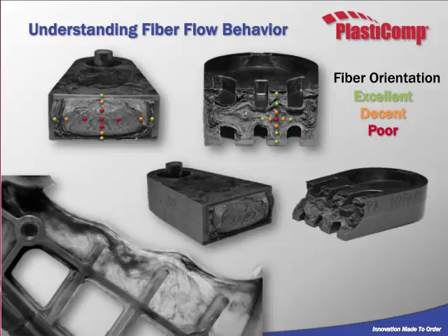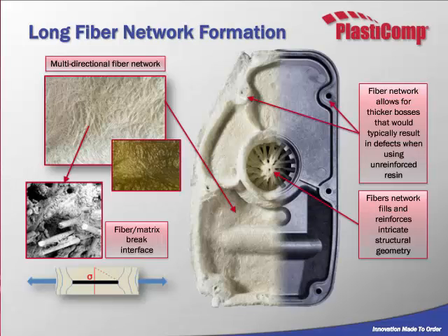it has to rip through more interfacial area to reach that break, which means it took a lot more force to get it there. And on the very bottom, you see an image of a primed part, where originally there was virgin resin in the mold, and we were priming in, adding fiber and pumping it through afterwards. So this is a rare occurrence where you get to see the 7-micron wide fibers filling a part. It gives you a different point of view of just how fine these fibers are as they slide through. I always thought that was interesting.